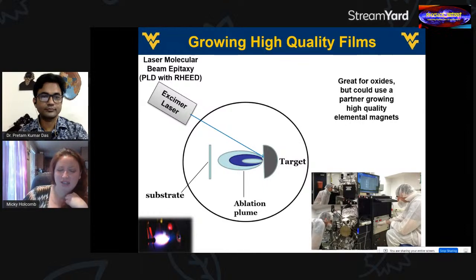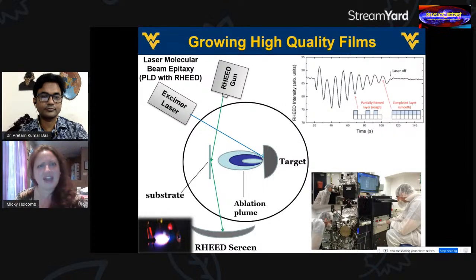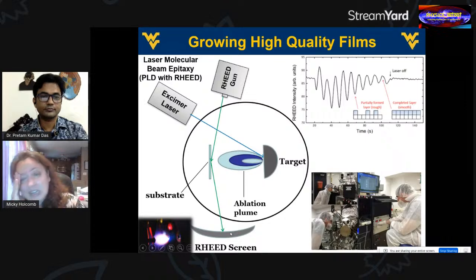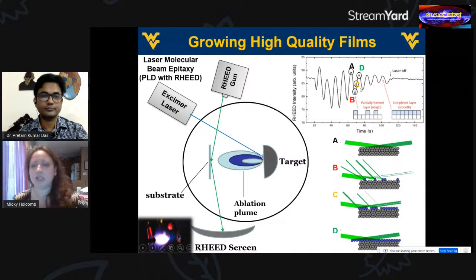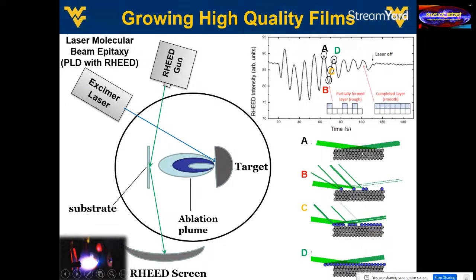But if you do everything just right, you can actually monitor as you grow with a reflection high energy electron diffraction beam. And if you monitor the diffraction pattern, mainly people just look at the main spot, but there's a whole pattern here that one can utilize. What basically happens is you get these oscillations. So I have a picture for this. So you start with a very smooth substrate, and you're coming in at a grazing angle. So your electron beam is hitting the sample, and most of it is going to reflect off towards the detector. So if you have a very smooth substrate, you're going to get a very strong signal out of it.